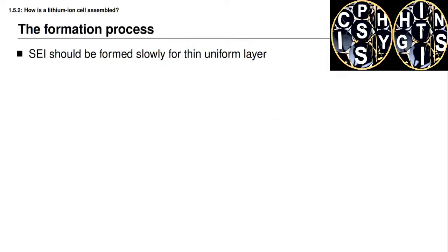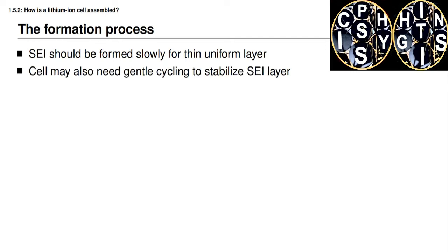We would like this SEI layer to be as thin as possible because we don't want to have excessive capacity loss. We want it to be as uniform in thickness as possible so that it doesn't easily break down at a later point in time. And this is most easily achieved if we form this layer slowly. So we form the layer by charging the cell very slowly for its very first time. And then after that, it may turn out to be valuable to gently charge and discharge, otherwise known as cycle, the battery cell a few times to stabilize the SEI layer before this cell is delivered to the consumer.